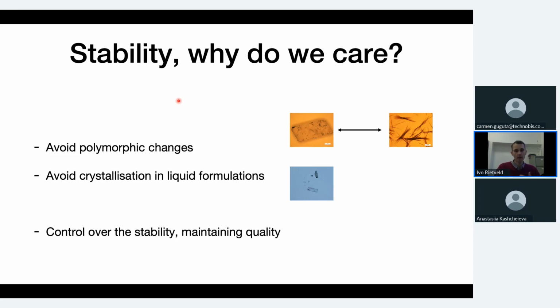etc. But on the other hand, this presentation obviously will be about polymorphism, about the crystals that we have and that we can use in, say, a solid state formulation. But the whole problem also exists the other way around. When you actually have a liquid solution and you want to avoid crystallization also there, you have to be careful about the polymorphs, because if you indeed hit a polymorph that is much lower in solubility, as the famous case of ritonavir, for example, you get a crystallization that you don't intend, and you also lose the efficacy of your drug system.